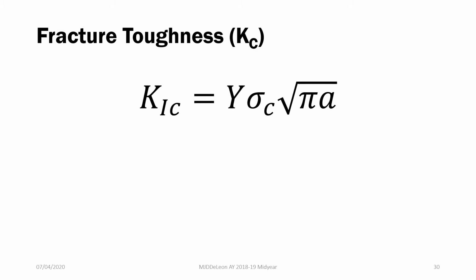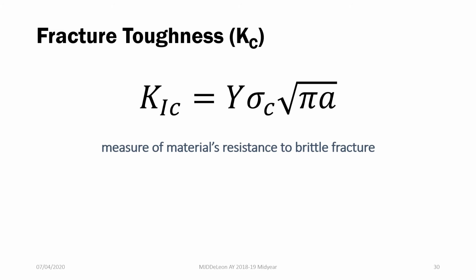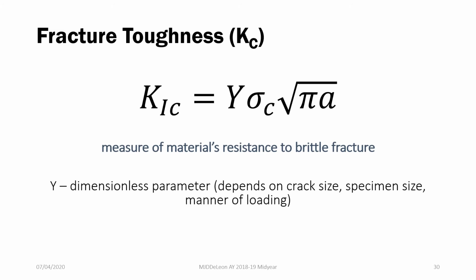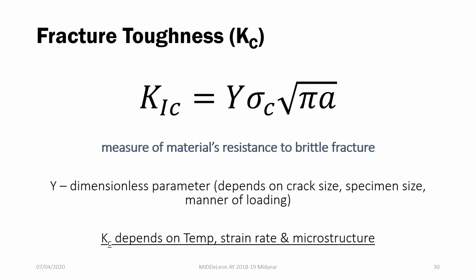Fracture toughness, or Kc, is used to determine the material's resistance to brittle fracture, where y is a dimensionless parameter which depends on the crack size, specimen size, and the manner of loading. So we usually have a table of values for this y. Sigma c is your critical stress from Griffith's criterion, and a is the length of the crack.